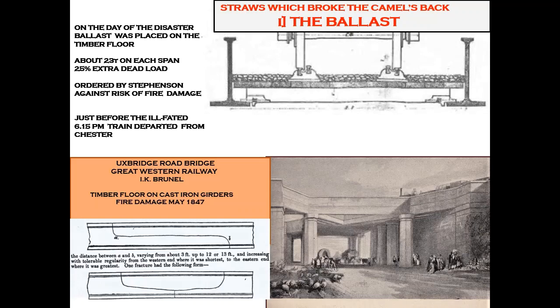The same day as the collapse, and 1 hour in advance of the train which caused the collapse, ballast was placed on the timber decking. And this had been ordered by Stephenson against the risk of fire damage, because earlier that month a bridge on the Great Western Railway under Brunel had obtained fire damage from cinders dropping from the steam locomotives, and the fire in fact severely damaged and cracked cast iron beams, which all had to be replaced. So Stephenson got concerned. He ordered this ballast to be placed. So it was just before our fatal train, so it must be, I believe, a factor.